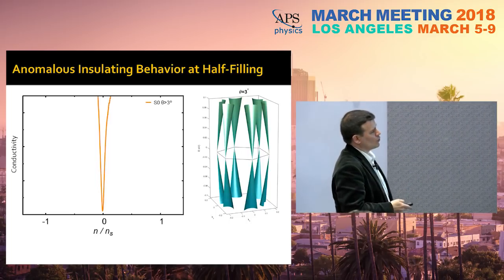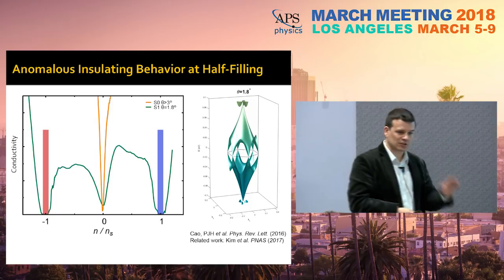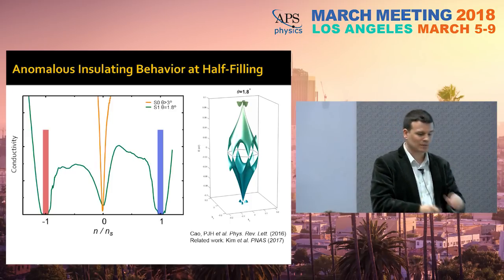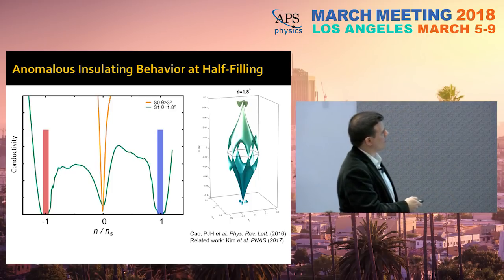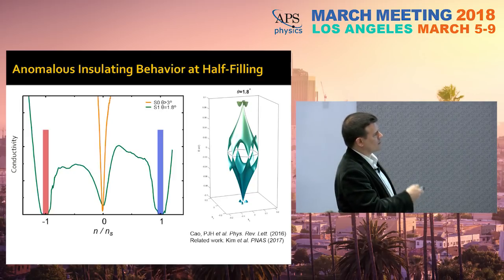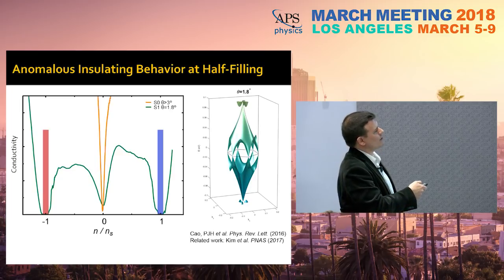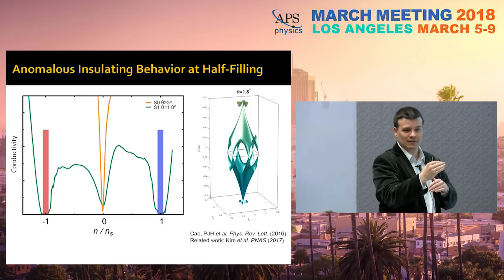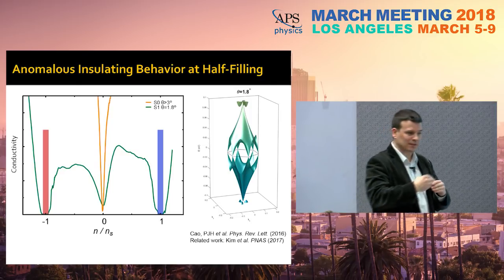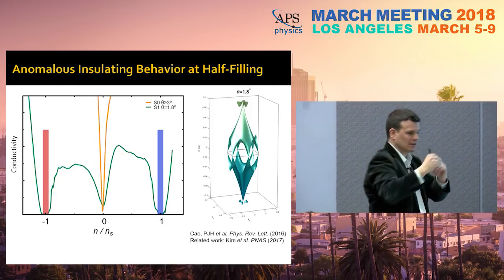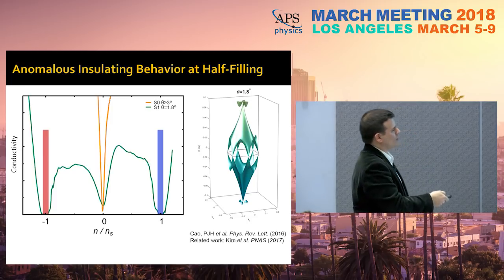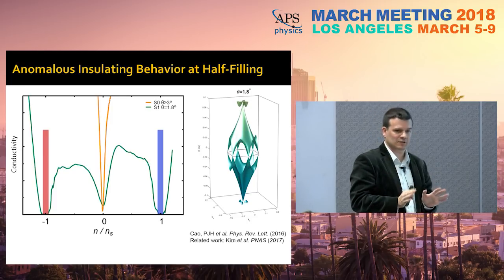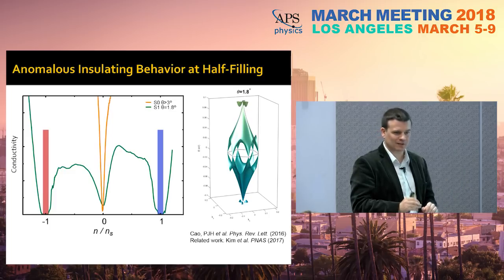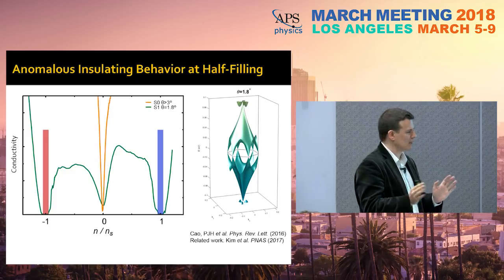So if I now go to 1.8 degrees, it's not yet the magic angle, but it's a small twist angle. The conductance as a function of density, near charge neutrality, still looks like graphene. However, it starts increasing, but we get an insulating behavior when we completely fill the band. Now, this is easy to understand. When you completely fill the band, then you have to go to the next band. There's a band gap in between the two bands, so you go insulating. This is something that we more or less expect. The details are actually quite a bit more complicated, but you can easily imagine this.